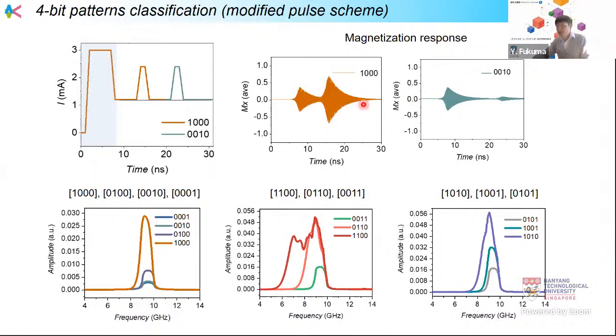What we can see here is a clear difference between 1 0 0 0 or 1 1 0 0. By using the fast Fourier transform, we can convert from time domain data to frequency domain data. We can clearly see the difference among the 4 different patterns. For example, here, in the case of 1 1 0 0 and 0 1 0 0, we can see a clear difference like this.